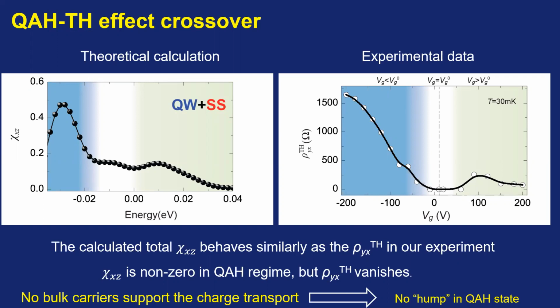Both show this kind of asymmetric phenomenon between the p-doped and n-doped regimes. The reason is that we know the magnetic exchange gap in this kind of magnetic TI film is usually much closer to the bulk valence band. So the only difference between these two figures is in the charge neutral point regime. We can say that in this one, it shows the quantum anomalous Hall regime. Although here we get that χxz is non-zero, there is no topological Hall effect in our experiment.